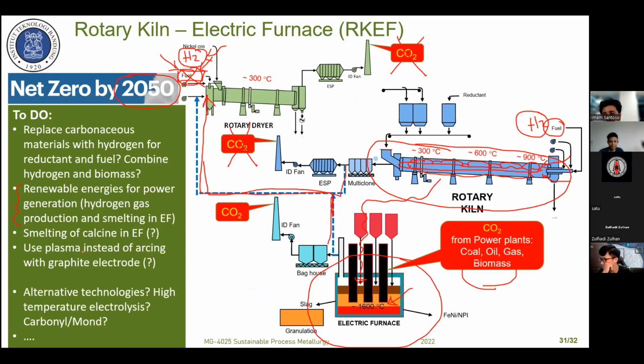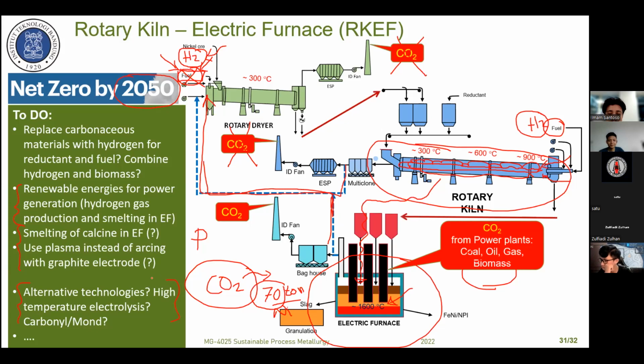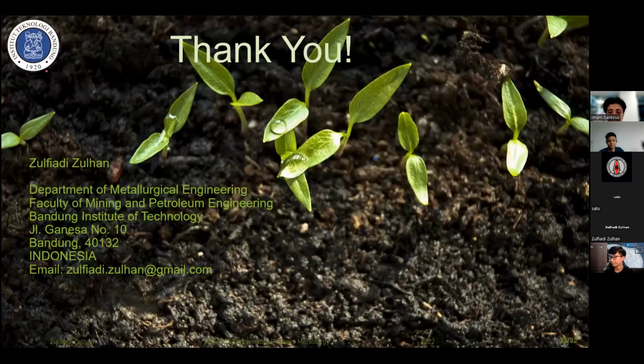The other thing we should think about is a future alternative method to reduce the CO2 emission. Currently, if we use a power plant from coal, the CO2 emission is around 70 tons per ton of nickel. So CO2 is around 70 tons per ton of nickel. It's very high. We should find another way. Okay, that's all. Thank you very much for the attention.